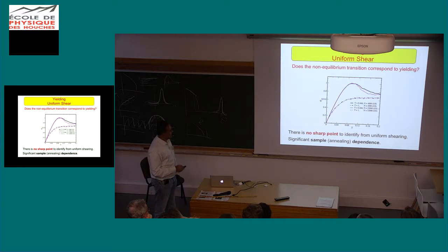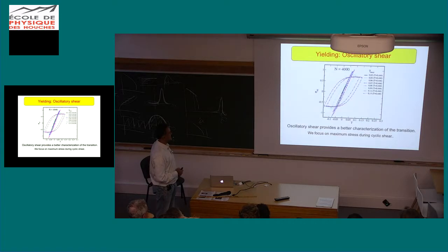And here I show the two initial samples that I have, the poorly annealed glass and the well annealed glass, at two different system sizes for cross check. And basically in both cases there isn't a very clear point at which one can identify a transition to have happened. This picture is in contrast with what one finds in looking at cyclic deformation.